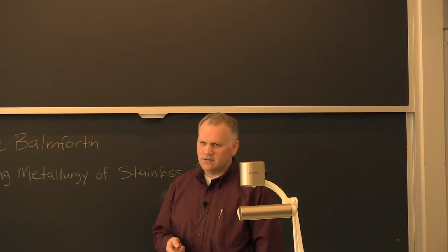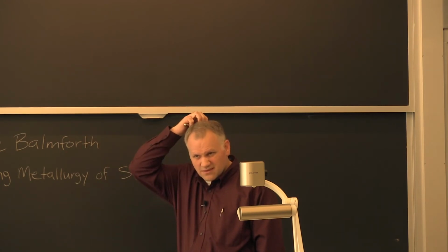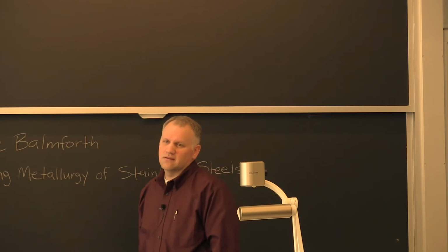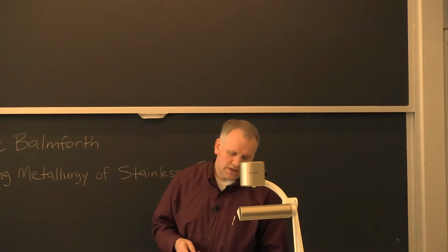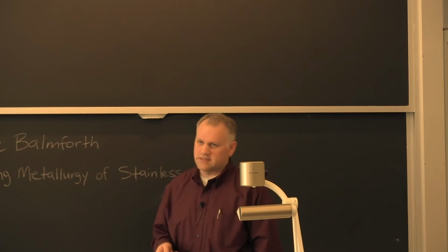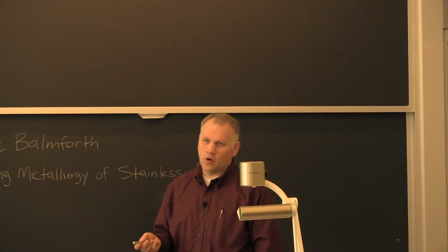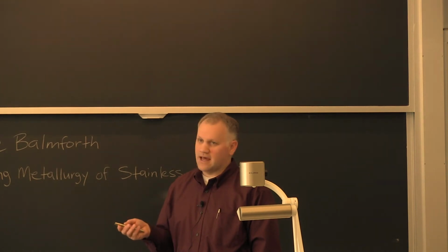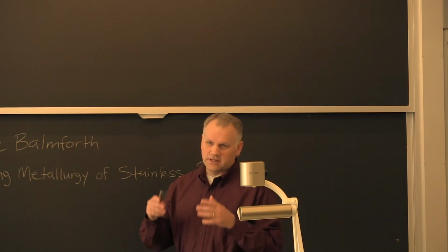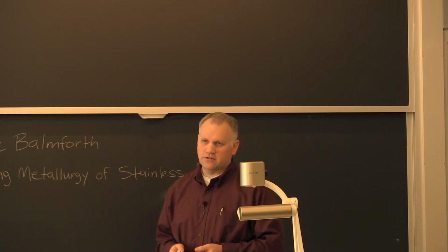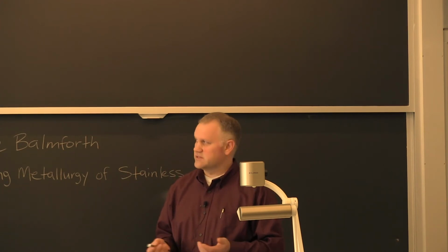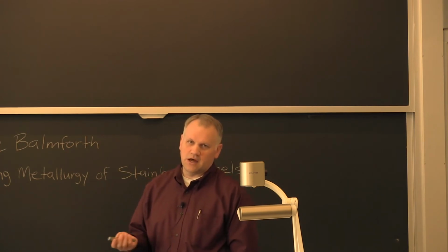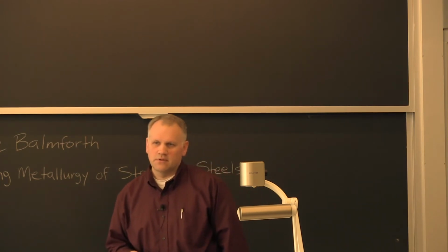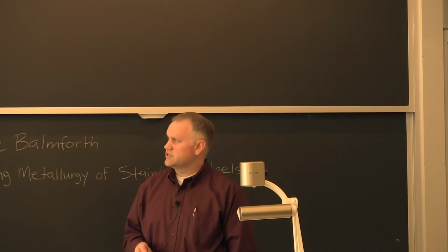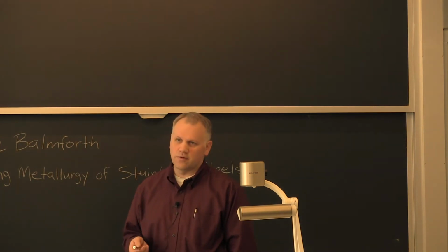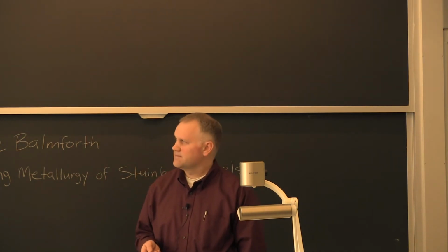What is it about austenitic alloy that makes it non-magnetic, especially considering it has a lot of nickel in it? Well, the nickel in this alloy system is an austenite promoter, and so the austenitic alloys solidify with a face-centered cubic microstructure, which is an austenitic non-magnetic microstructure. So it's really just the austenite that's formed is a non-magnetic structure.